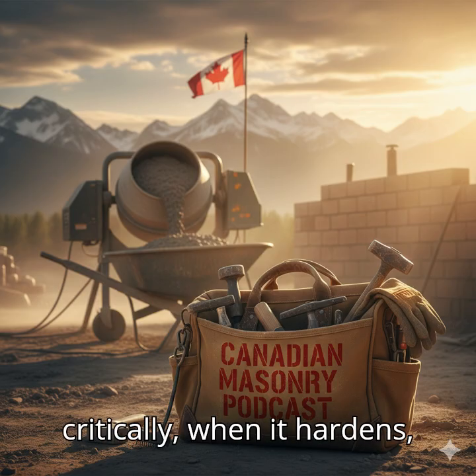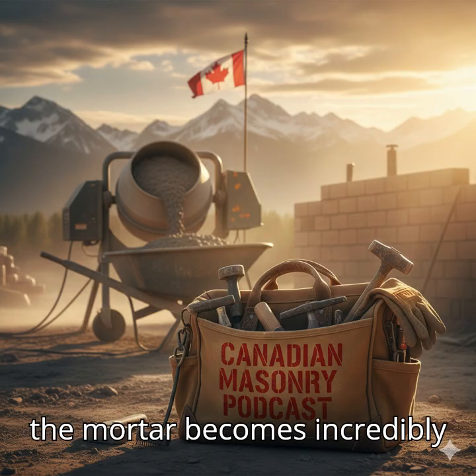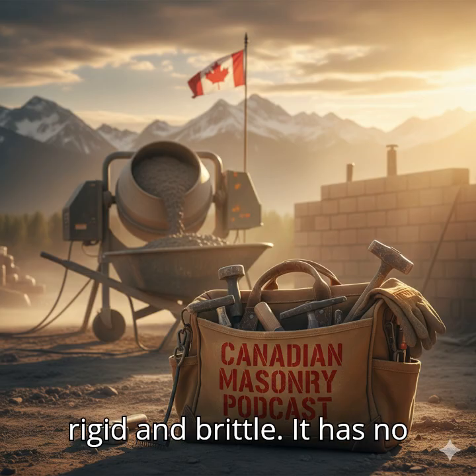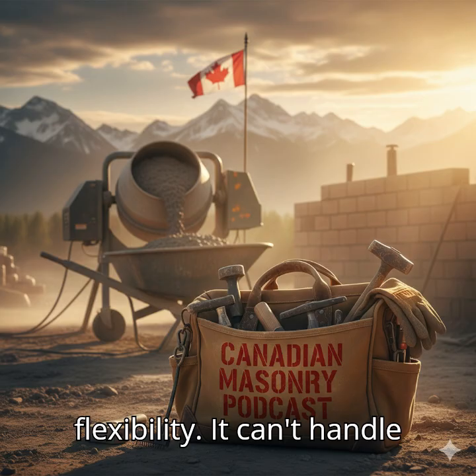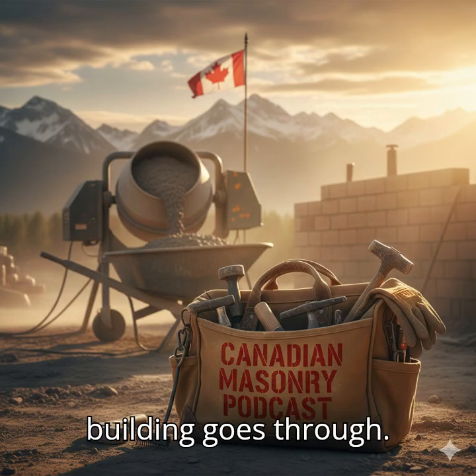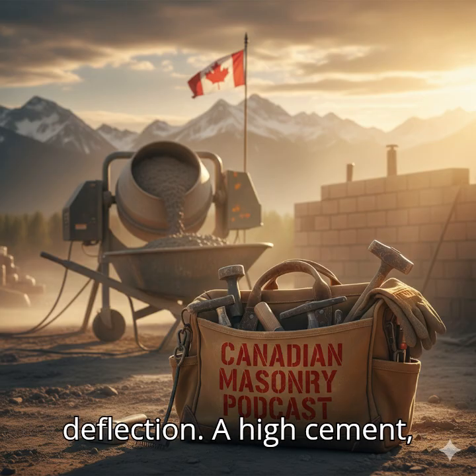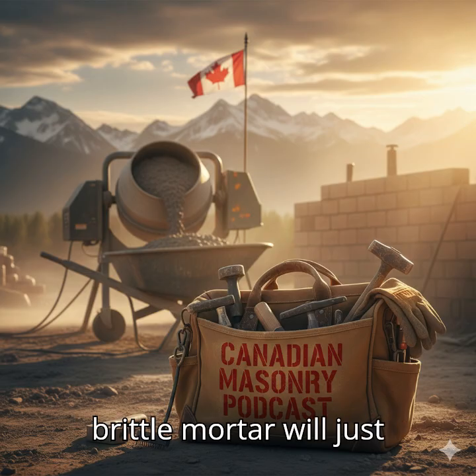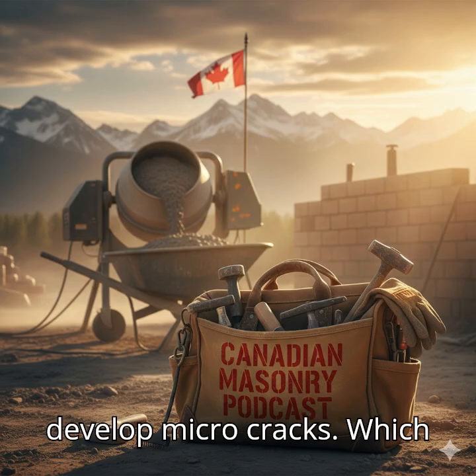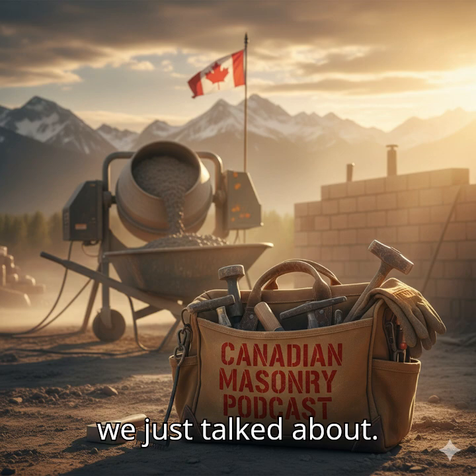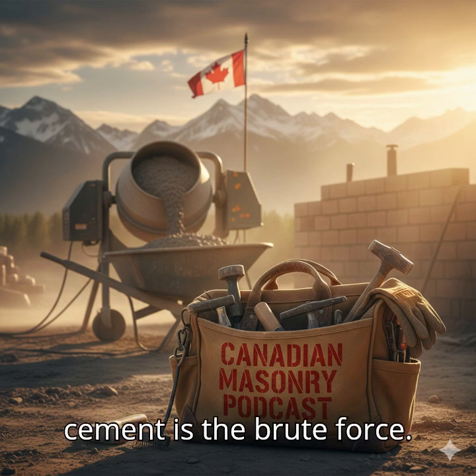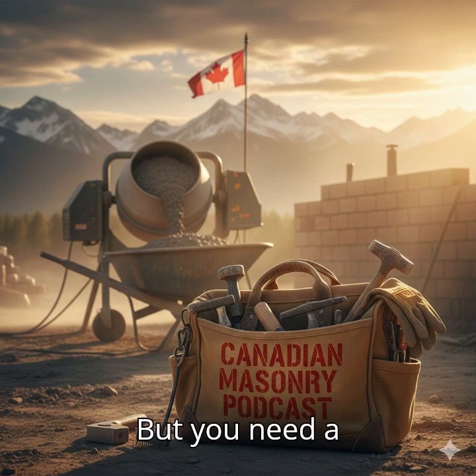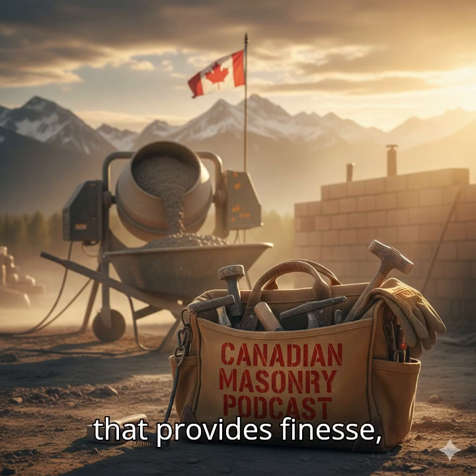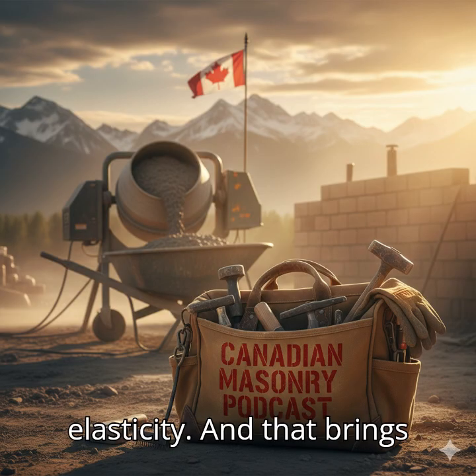More critically, when it hardens, the mortar becomes incredibly rigid and brittle. It has no flexibility. It can't handle the tiny movements that every building goes through: thermal expansion, wind deflection. A high cement, brittle mortar will just develop microcracks. Which compromises the weather seal we just talked about. Exactly. It lets water in. So cement is the brute force. But you need a countermeasure. Something that provides finesse, elasticity.